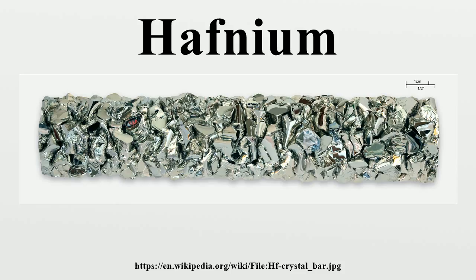Hafnium carbide is the most refractory binary compound known, with a melting point over 3890 degrees Celsius, and hafnium nitride is the most refractory of all known metal nitrides, with a melting point of 3310 degrees Celsius. This has led to proposals that hafnium or its carbides might be useful as construction materials that are subjected to very high temperatures. The mixed carbide tantalum hafnium carbide possesses the highest melting point of any currently known compound, 4215 degrees Celsius. Recent supercomputer simulations suggest a hafnium alloy with a melting point of 4400 K.